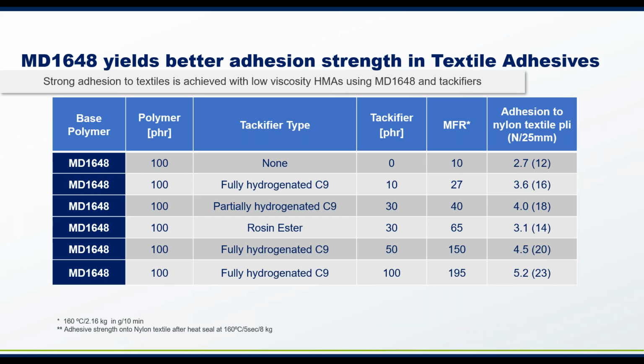MD1648 can also be formulated into a hot melt adhesive for textile applications. The table here shows the melt flow rate and adhesion strength to nylon textile for MD1648 with and without adding the tackifier. And you can see that the adhesion strength can be doubled by formulating MD1648 with a tackifier, and the melt flow is also significantly higher.